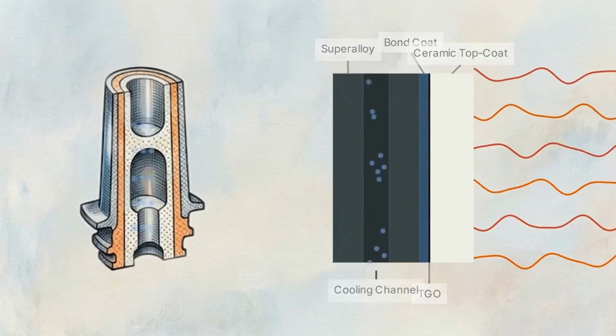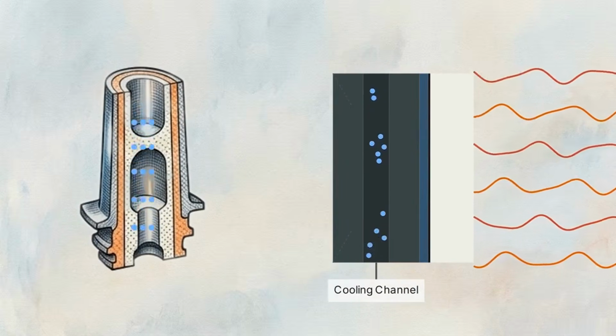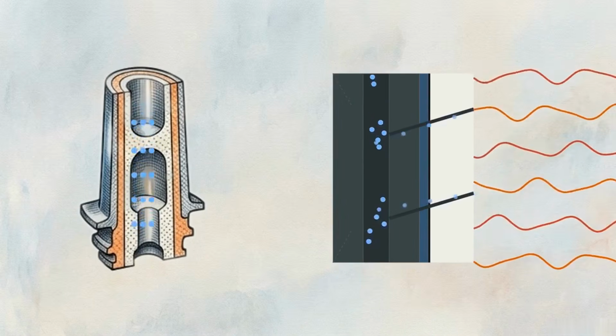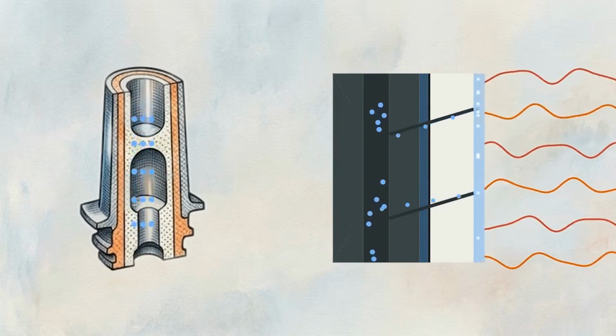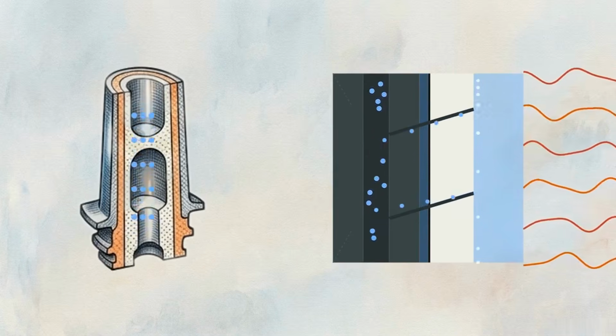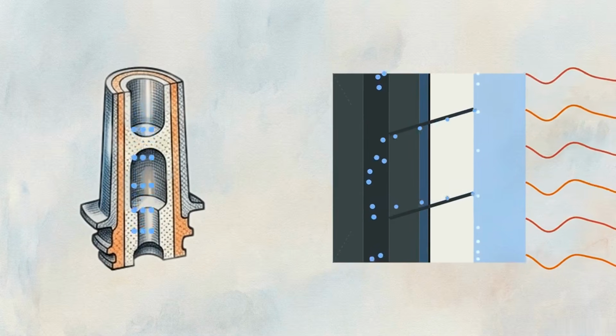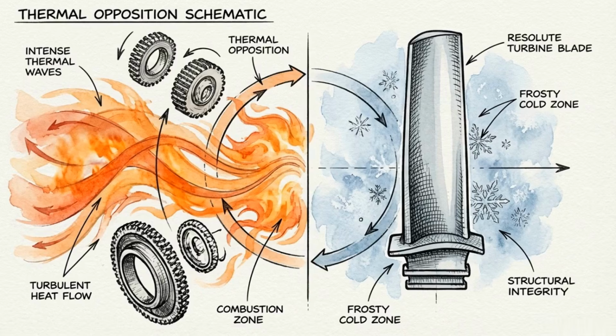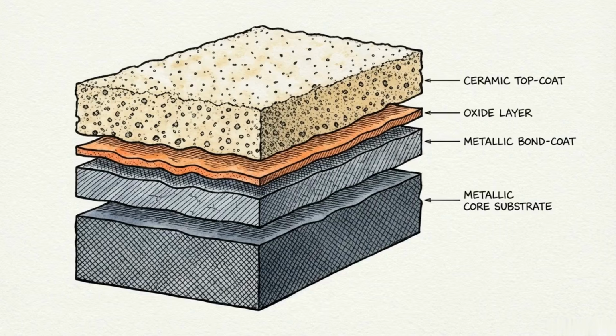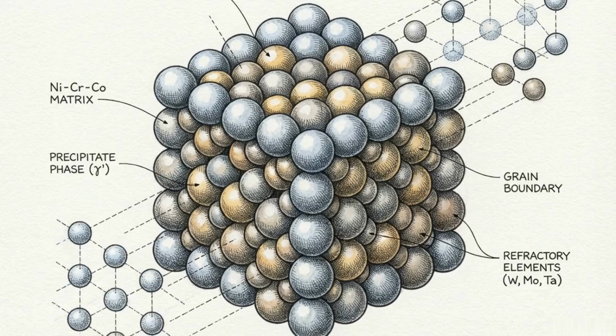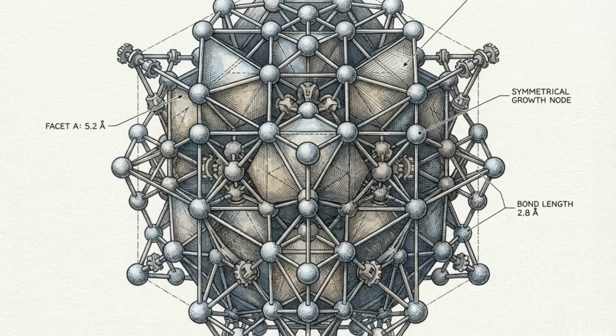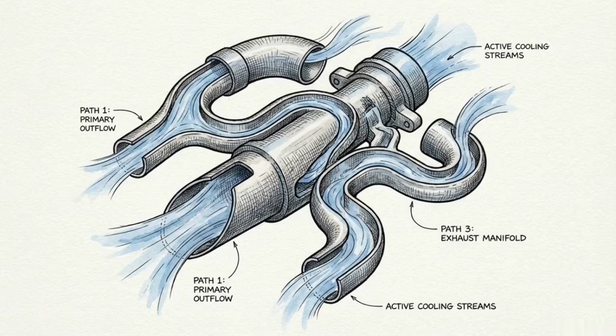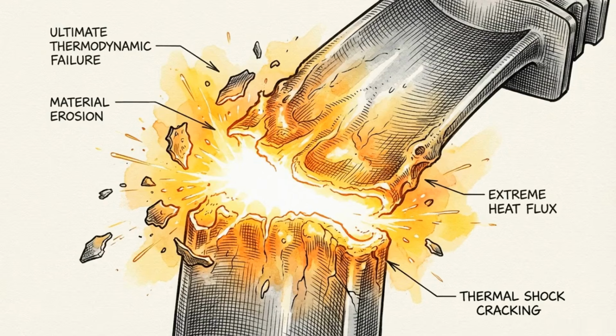Then, hollow core passageways route cooler compressor air out through laser-drilled surface holes, creating a flowing film of air that physically pushes the 1600-degree gas away from the blade. Getting a piece of metal to survive hell requires an exhaustively layered defense, with precise chemistry, flawless structural growth, and constant active cooling. We have pushed nickel-based superalloys to their absolute thermodynamic limit.